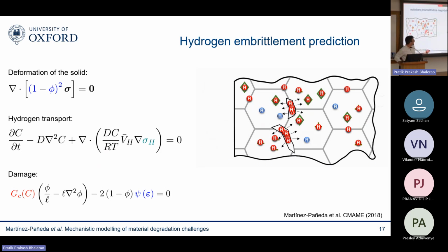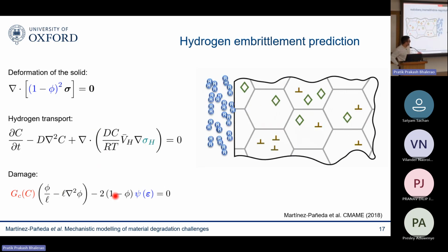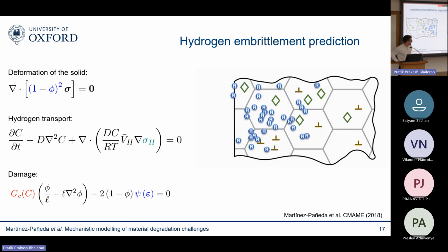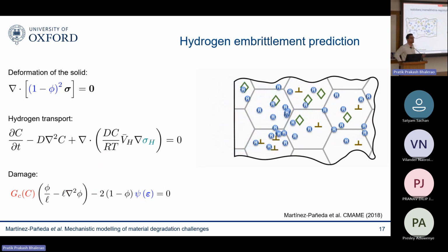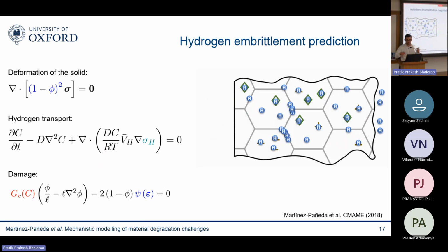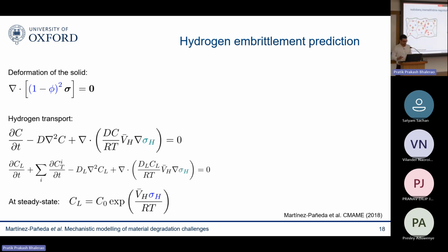So of course, again, the damage will reduce your load carrying capacity, as we said before. The hydrogen transport equation, you can see here, hydrogen moves driven by gradients of concentration, but also by gradients of hydrostatic stress. So the coupling with mechanics is quite strong. And then finally, you have the damage, which evolves based on the energy that you're storing in your material, but also your resistance to fracture, which will be dependent on the hydrogen concentration. These are the strong couplings. So let me discuss them a bit independently.